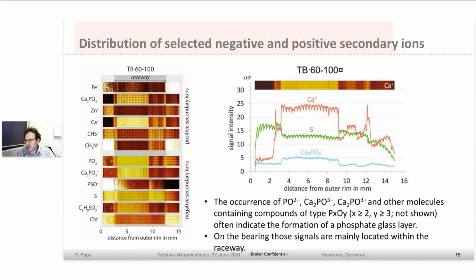And there are some very interesting elements that we can see, like the calcium from the additive, or also the phosphate classes that are formed on the surface. On the right, there's exemplary the calcium signal, and in combination, the diagram with the sulfur and also the calcium phosphate classes formed on the surface. And we can see also that the slip-to-roll ratio has an influence on how this kind of tribofilm is formed.